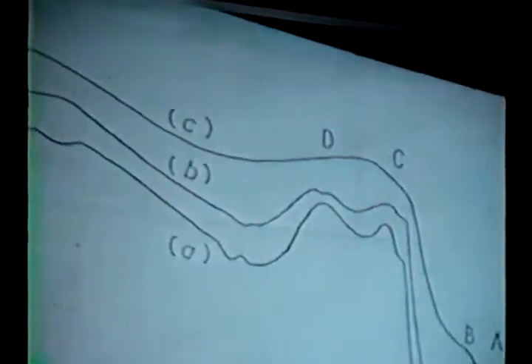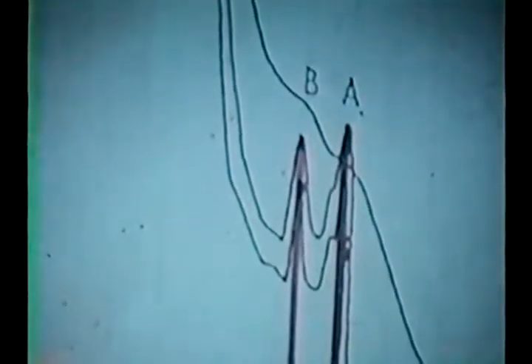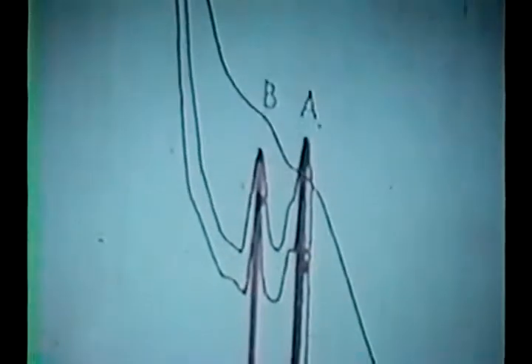In the moly sulfide alone, there is an electronic spectrum which shows a big difference between an intercalated alkali compound and the moly disulfide without the alkali compound. The difference between the two is that the intercalated alkali ion, which originally is not an ion, dumps an electron into the MoS2 layer, and the MoS2 layer becomes negatively charged. Before that happens, there is what is known as an exciton spectrum, whose essential interpretation is a dumping of an electron from the sulfur into an empty orbital of the molybdenum 4+, and this means that it is associated with the presence of an empty state in the molybdenum.